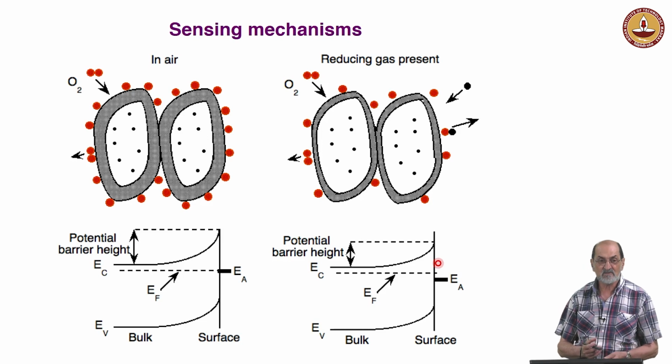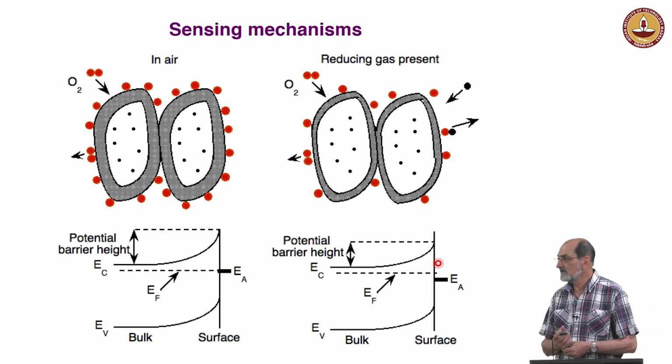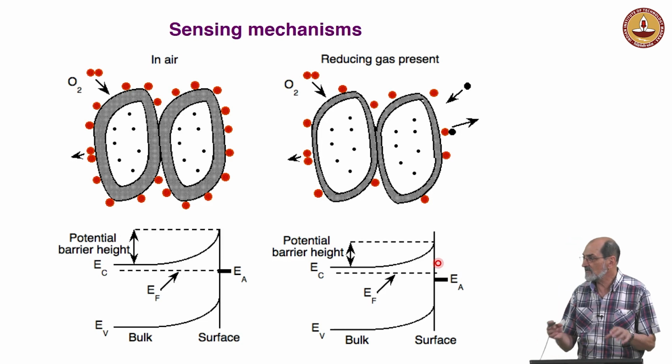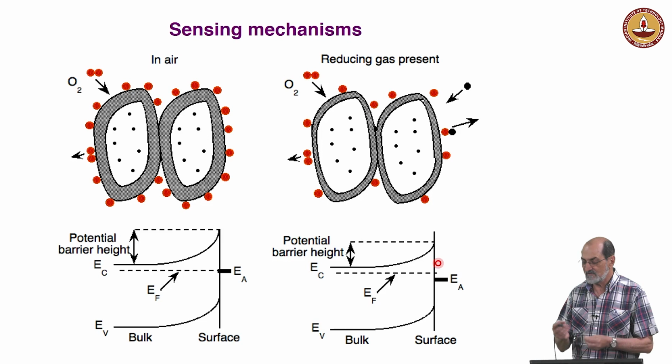At low temperatures, all the oxygen covers the surface completely, and the system does not work because from a catalytic point of view, it becomes poisoned. All the active sites are occupied, and you cannot produce a reaction for things to change. This is what happens at low temperature.